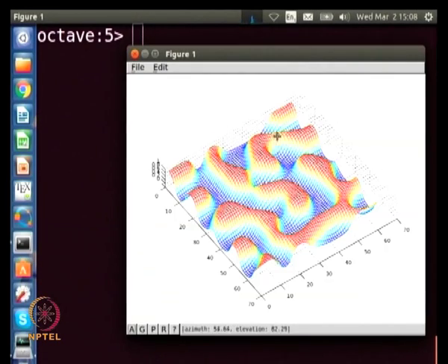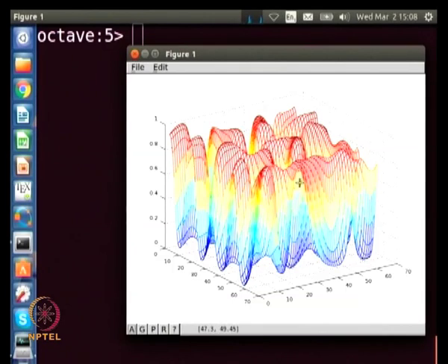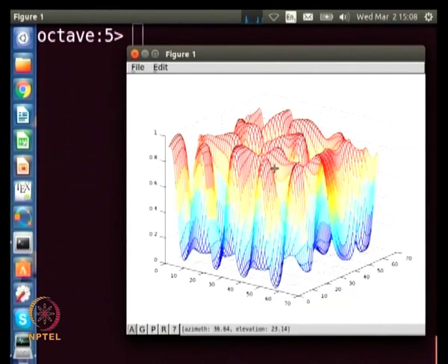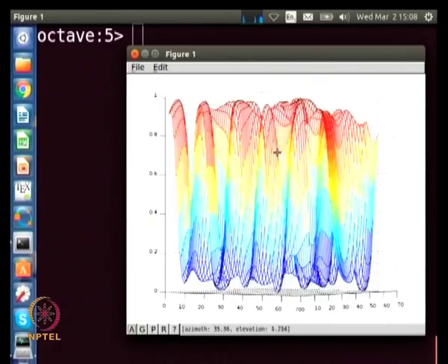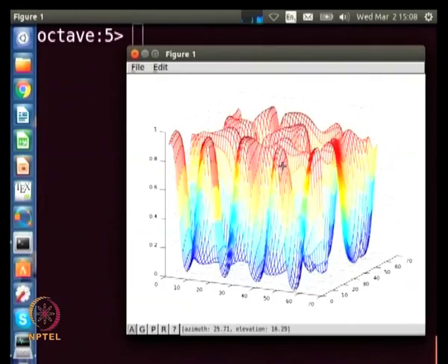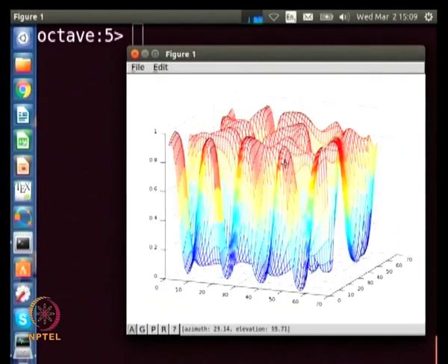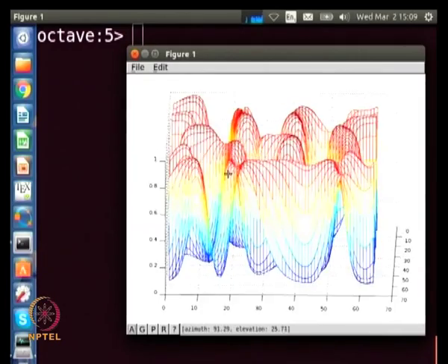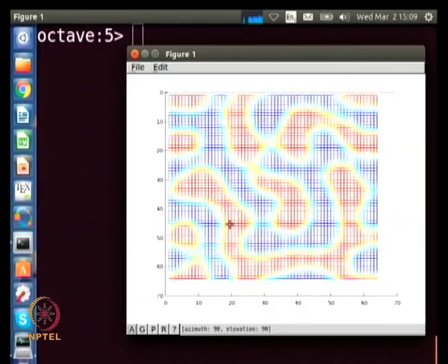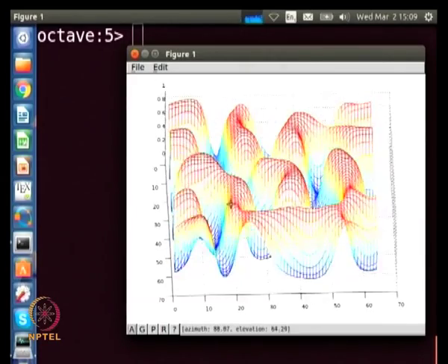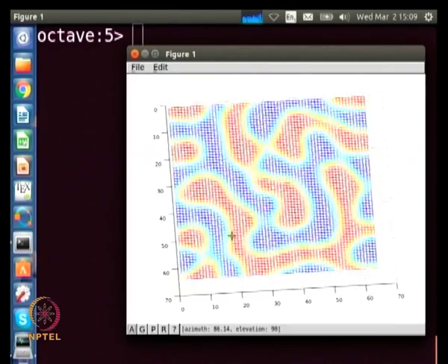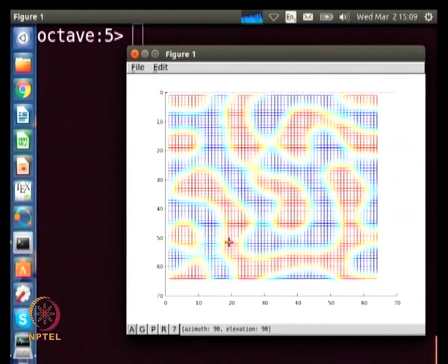So, the entire microstructure consists of composition regions where it is 0 and composition regions where it is 1, and there is this effect of the interface on the composition part, which we will see clearly when we look at the simpler precipitate growth case. So, this is the microstructure, we are looking top down, and that is why it looks like this. Okay. So, in this figure, whatever is all blue is basically A rich, all red is basically B rich, and you can see that the interface is a region where it goes from red to blue.